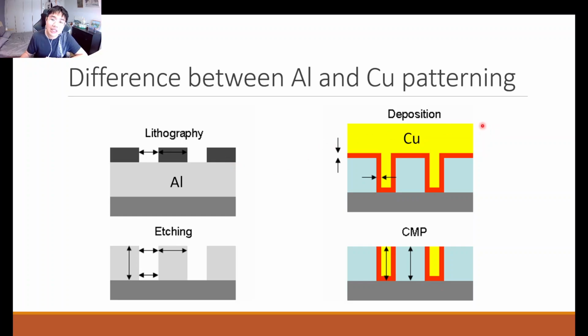However, for copper, the scheme is slightly different. We have to deposit a seed layer and plate copper into the gaps before polishing the excess copper down. In this way, we get the copper into the gaps in the layer below. Maybe this can be an oxide layer, some dielectric layer. It's the gaps in the dielectric layer that define where your copper goes. So this is obviously a different scheme compared to aluminum-based patterning, which is an etching-based mechanism, whereas in this case for copper we do something called a Damascene process.